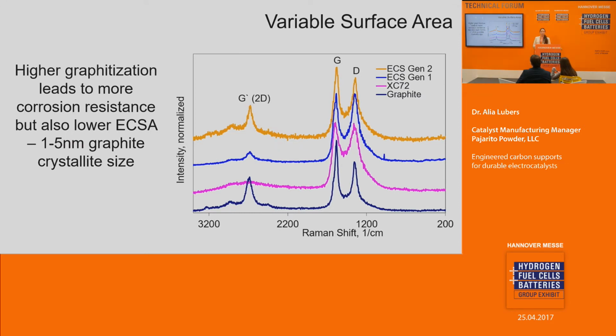Because the types of carbon within the support itself are very important, especially for durability. Generally, more graphitic carbon will lead to more stable and more durable support within the catalyst layer. And with our Varipore method, we are able to influence the degree of graphitization or disordered carbon. So comparing, this is a Raman spectra. The higher and the more narrow peaks, the more associated with that type of carbon. So if we have graphite, which has a very high graphite peak, less disordered peak, we can match the amount of graphite content of graphite itself, and we are also able to make more disordered materials as well. So depending on your needs, we have a high degree of customization in our ability to make these carbons.